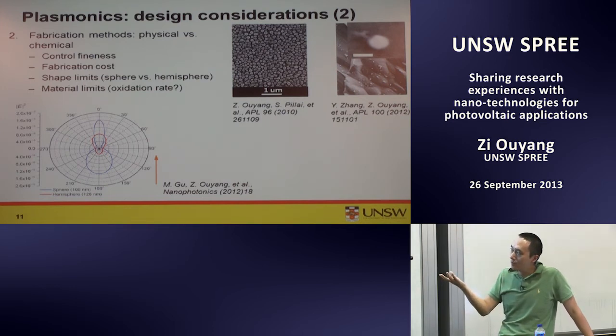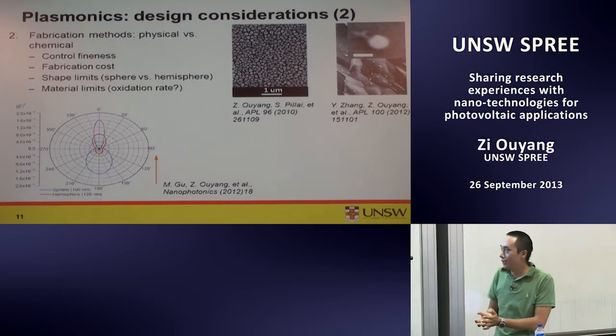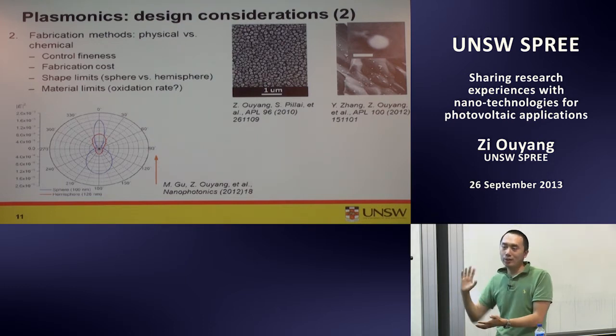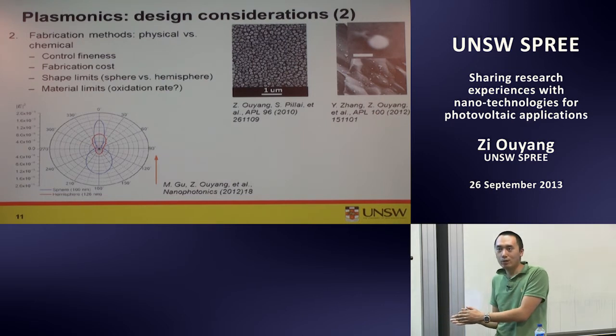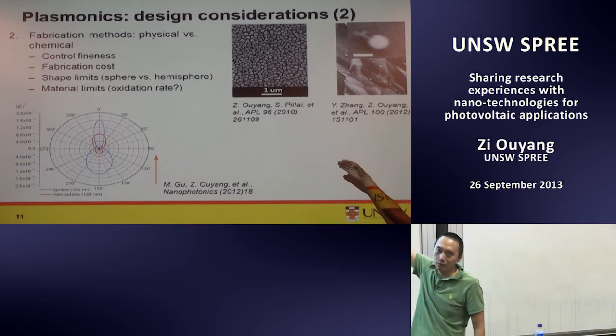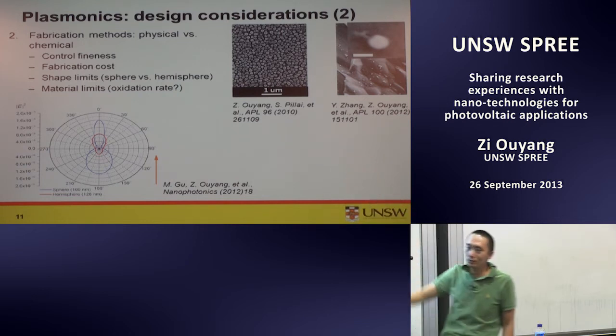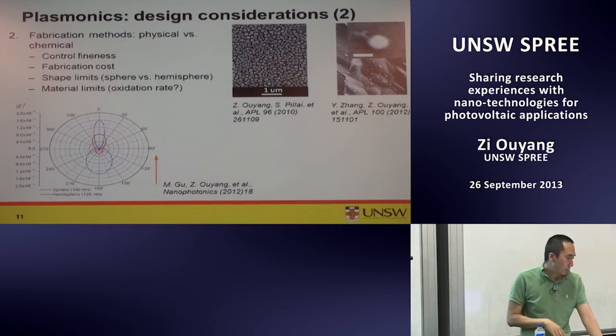For example, in this case, the hemisphere may be much more preferable for front side coating because you have a better anti-reflection effect. But for the nanoparticles which are spherically shaped, you probably put them on the back, because scattering to large angles is more important than forward or backward scattering, because you can easily put another back surface reflector behind the nanoparticles and reflect whatever is transmitted back to the solar cell. So it's just some considerations.